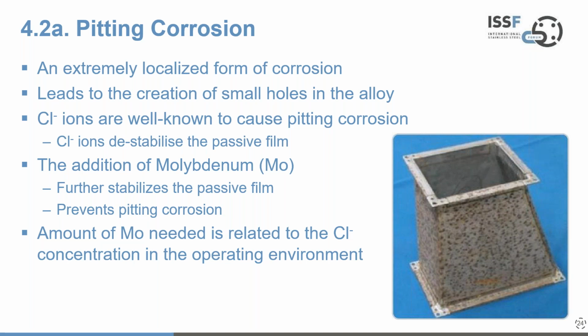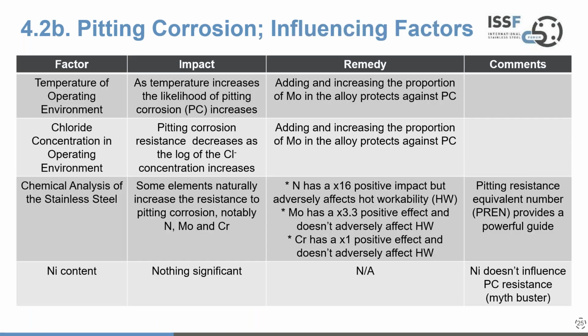But it's good to recognize that the amount of molybdenum needed is related to the chloride content of the operating environment. So it's not just as simple as saying add 2% molybdenum and you're sorted. You have to think a little more about the operating environment. It's also useful to highlight the influencing factors, and there's three core influencing factors here and one sort of urban myth that I'd like to dispel at the bottom of this table.